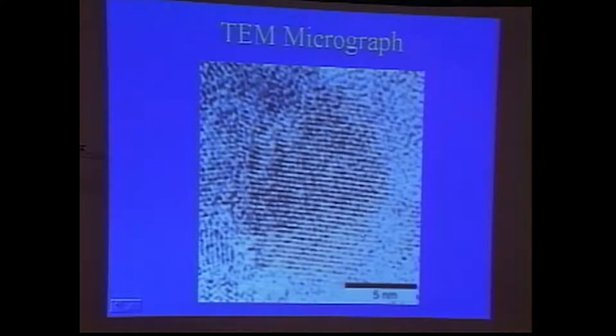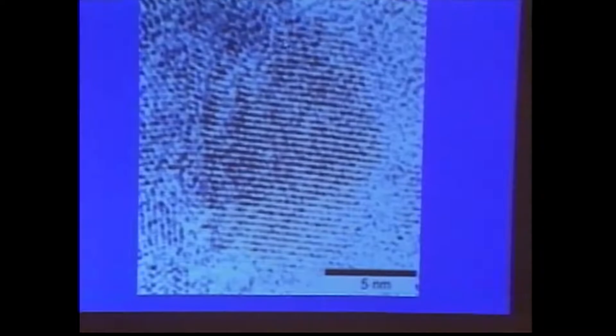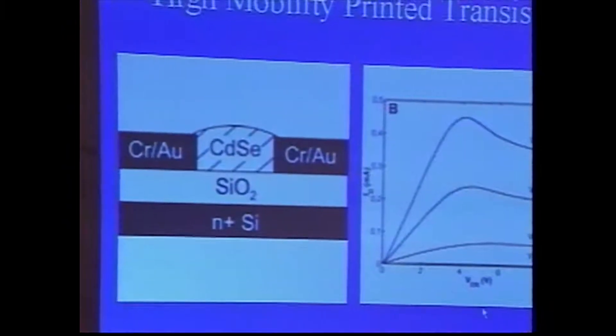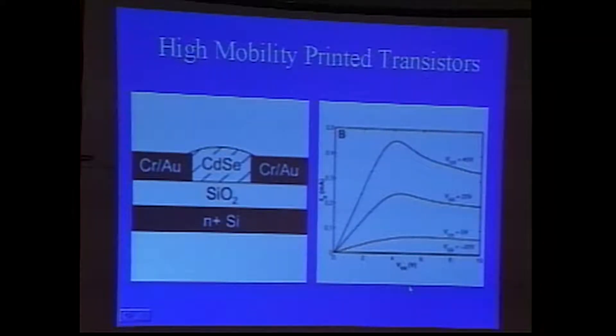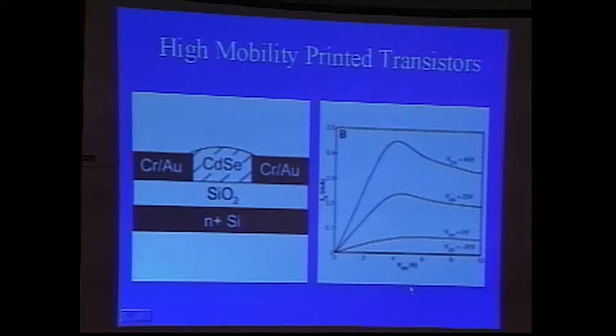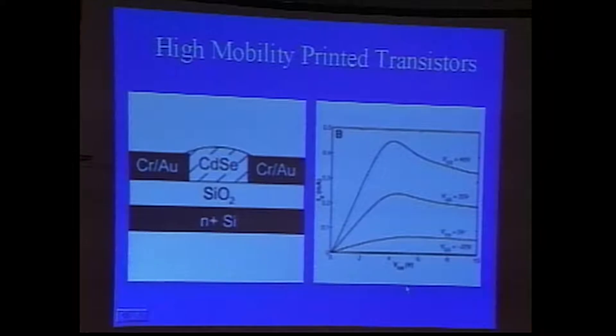When we take this material and put it down onto a surface, hundreds of these clusters come together. Their organic group pops off and they form crystalline sheets here out of which we can build transistors. The remarkable thing was that the clusters don't come together in an arbitrary orientation, but actually all of their crystal planes line up, which of course is the key to making high-quality devices.